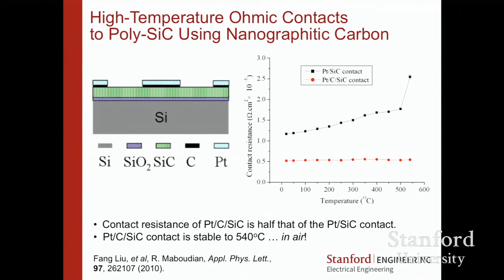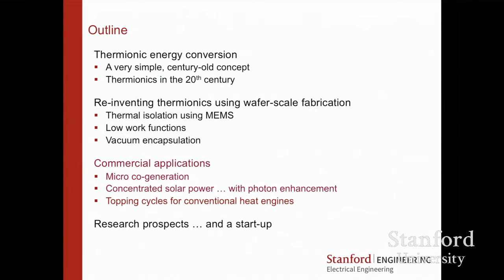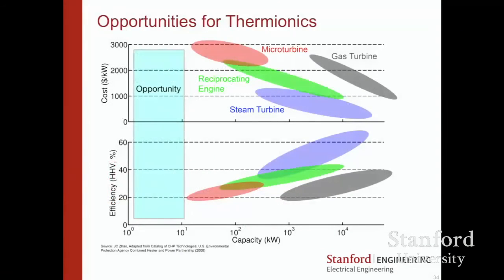I would point to a collaborator at Berkeley, Roya Maboudian, and her student Fang Liu. They looked at a contact that would use a new type of nanographitic carbon between silicon carbide and platinum. And their contact, really the limit of their furnace is 540 degrees. And the normal contact is beginning to fail. But what's really shocking recently is that they would run this in air. And so it's not in a vacuum at all. Things are oxidizing at hundreds and hundreds of centigrade. The carbon is not susceptible to that. They've sort of demonstrated, I think we can get the current out. So a lot of pieces, and have we really put it together yet? Well, I will tell you more when we wrap up.